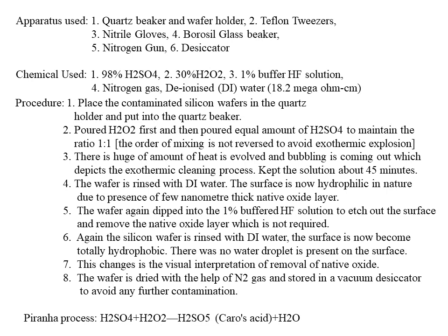If we do it in reverse, then a huge exothermic explosion can happen, so we are avoiding that explosion. We first pour H2O2 and then H2SO4 in an equal ratio, and we have to keep the entire system for just 40 to 45 minutes. A huge amount of bubble effervescence can come out during this cleaning process, along with a huge amount of heat. And after 40 to 45 minutes, we have to take